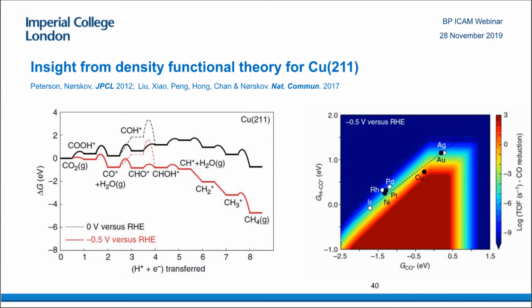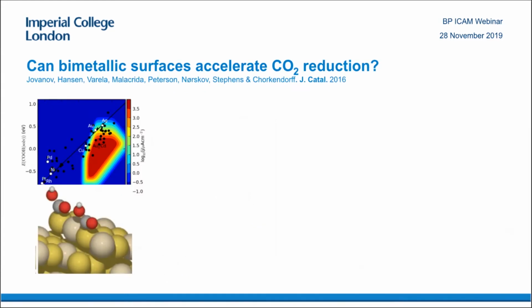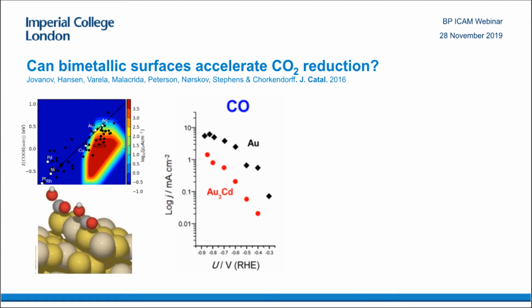So in collaboration with Jens Nørskov, who was at Stanford at the time, he had the idea that according to DFT calculations, if you looked at bimetallic catalysts, you could break these scaling relations and actually get much higher activity than the pure metals. So we actually tried this out. We looked at gold cadmium catalysts, which was supposed to be right at the sweet spot here.